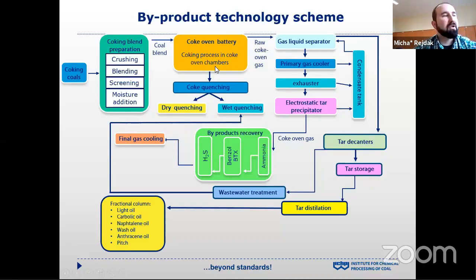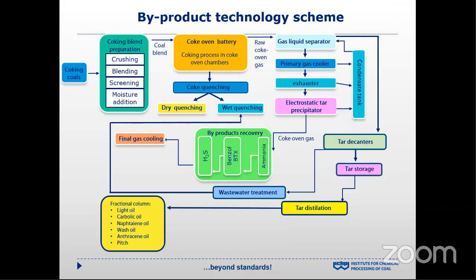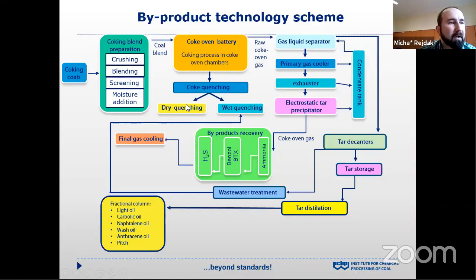Of course, the wet quenching process involves spraying coke with water in a special quenching tower, and then the cooled coke is transported to the wharf and then to the sorting plant. Dry quenching facilities consist in cooling the coke by passing inert gas through the coke bed. The gas extracts heat from the coke and transfers it to the water in the steam boiler. Of course, the gas is in a closed circuit.